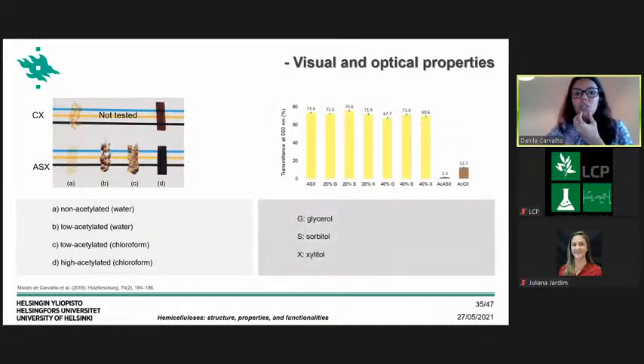In terms of color, or in terms of transparency, what we could see is that the films using the non-acetylated xylan were quite transparent. And in the case of the films prepared from the acetylated samples, they were from translucent to opaque. Although some variation depending on the plasticizer was observed, the range of the transmittance was quite similar for the various conditions. In the case of the xylan acetylated at low degree, we didn't succeed in forming continuous films using any of the solvents, either water or chloroform.